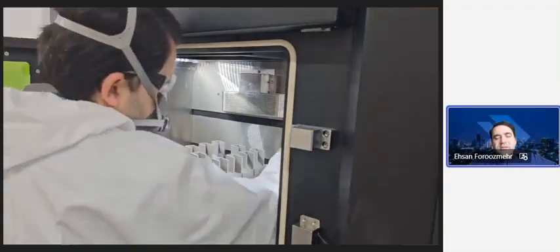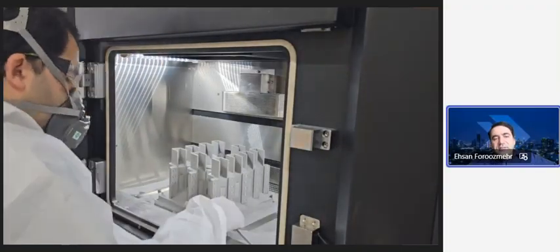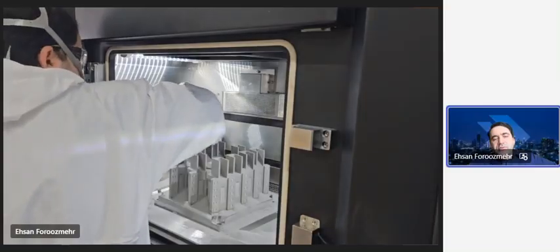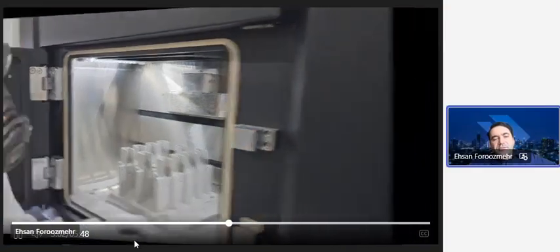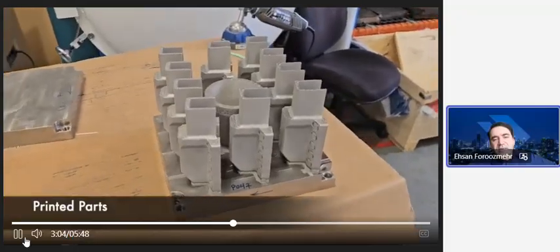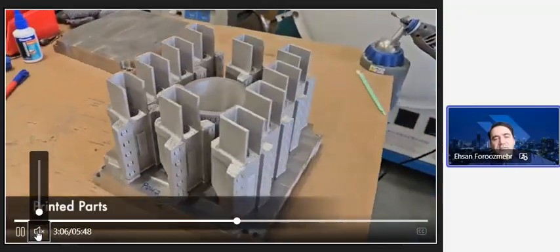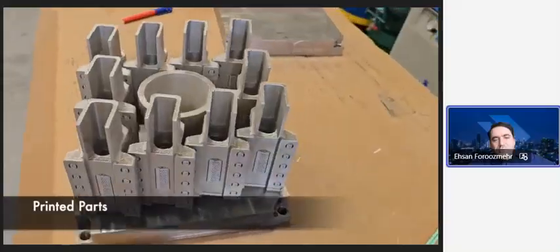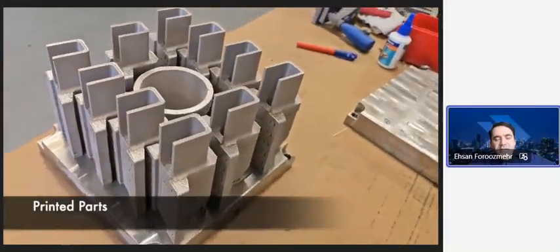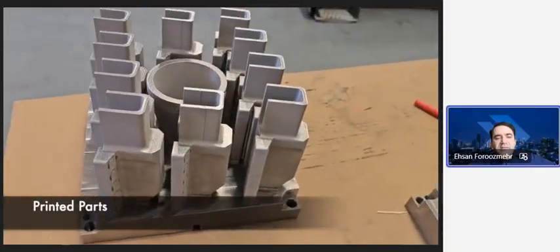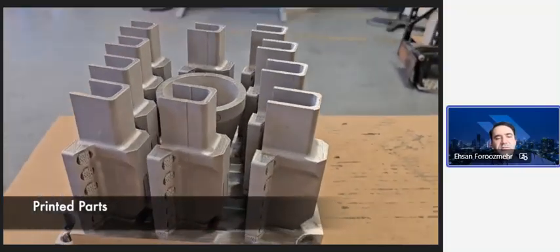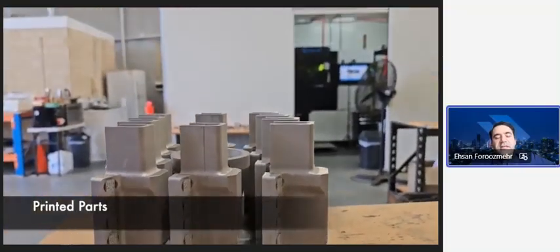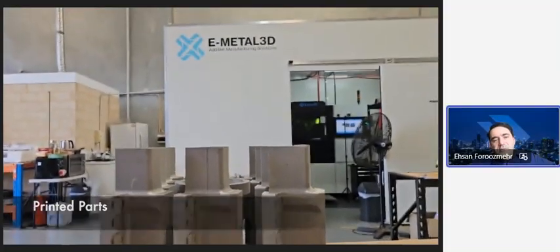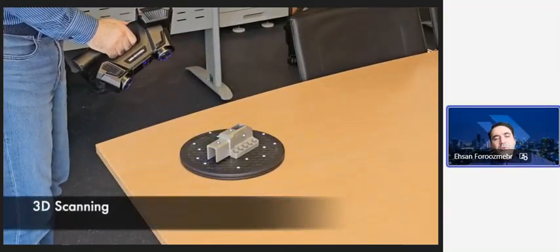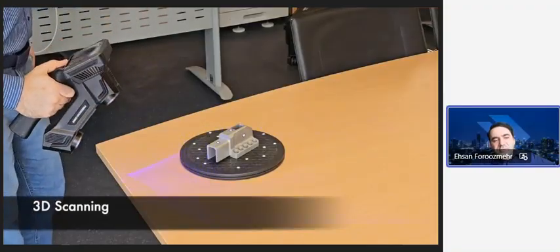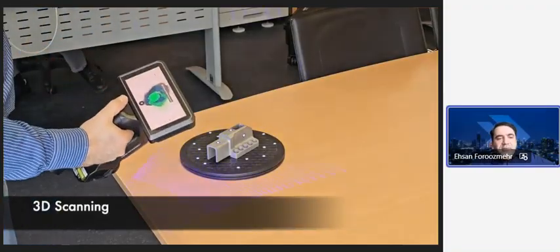So that is the end of the process for printing, but obviously you need to do some post-processing. For example, we need to get rid of all the supports that we added. The supports are not meant to be there. We had to put them there because we have overhangs and some limitations. We need to make sure that the part comes out properly. And if the surface requires more quality, then we can also do post-machining.